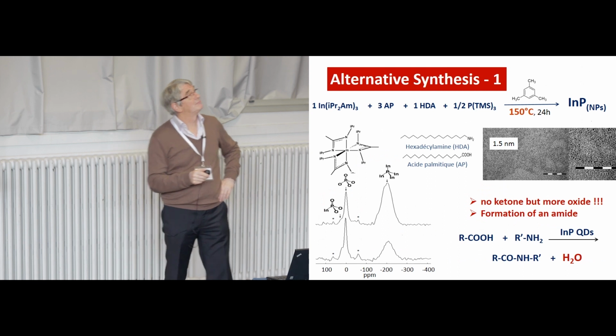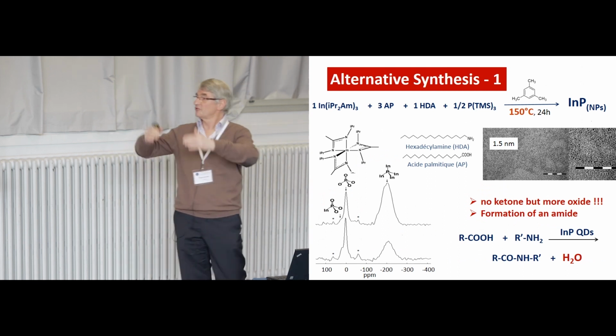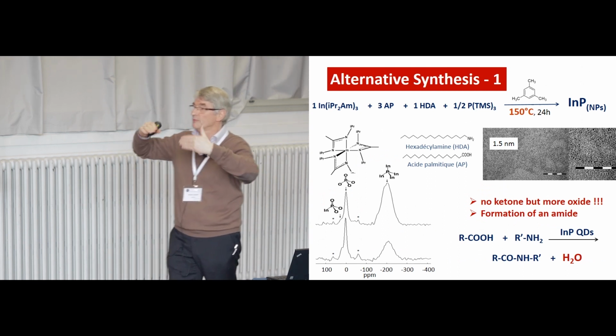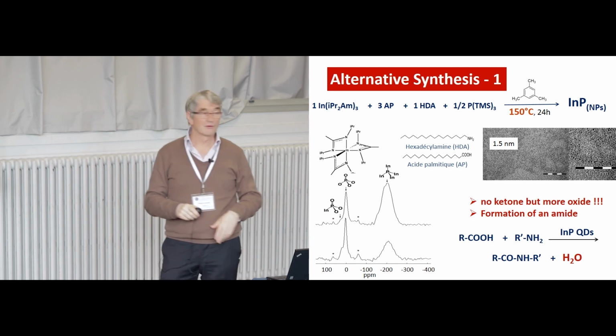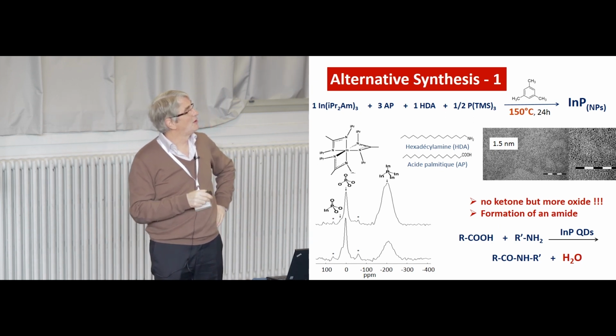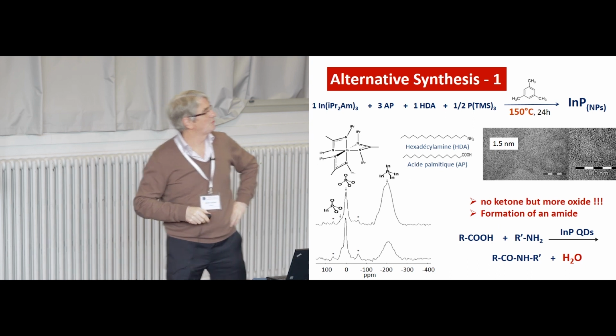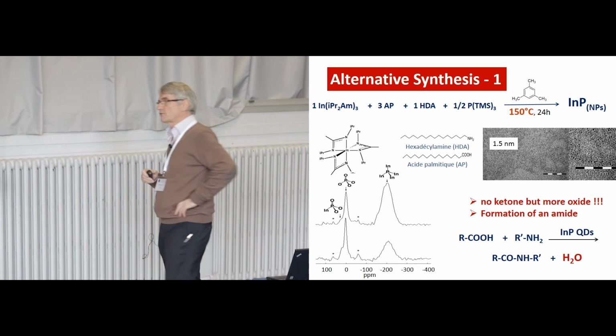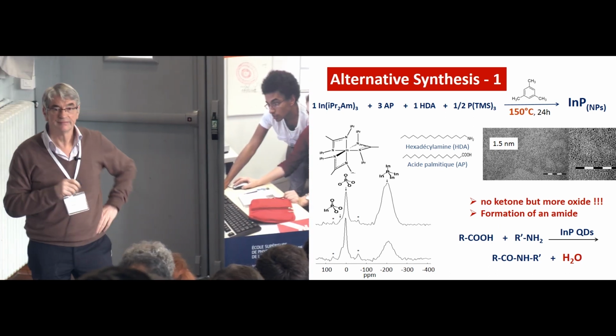So next, we put HDA. HDA will remove the water from the surface of the growing indium phosphide. We have, I did not put the size of the particles, they are 3.9 nanometer.